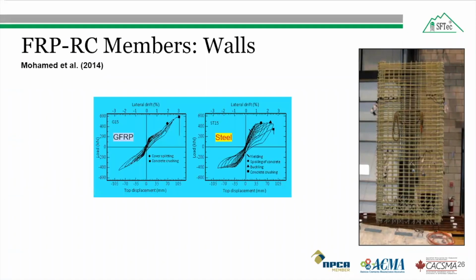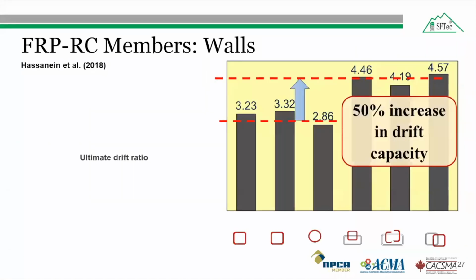concrete shear walls, and all the glass fiber reinforced polymer reinforced shear walls achieved flexural behavior with no sign of premature shear, sliding, bond, or anchorage failure, and they attained a drift ratio of over 3%. The advantage of the GFRP reinforcement was no permanent deformation at up to 80% of the ultimate capacity of the shear wall. In further testing of 6 full-scale shear walls with different boundary elements, it was observed that more confinement in the boundary element of the wall enhanced the drift capacity of the wall.